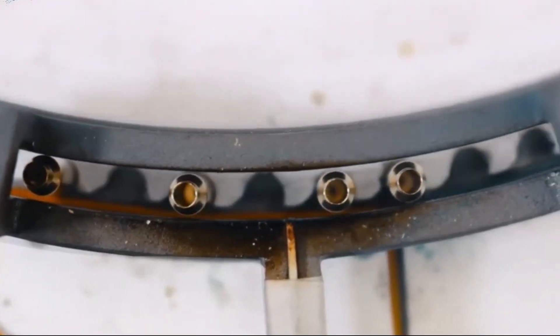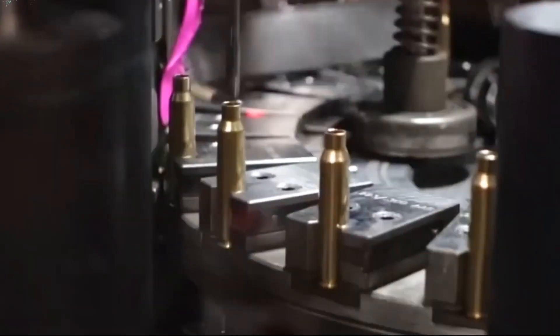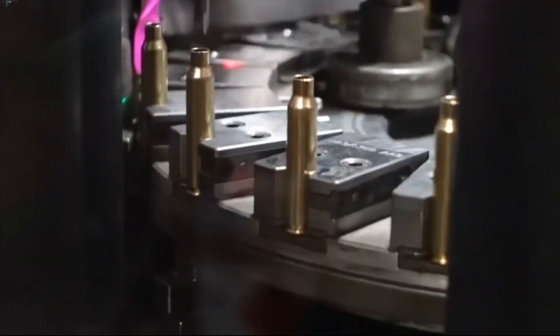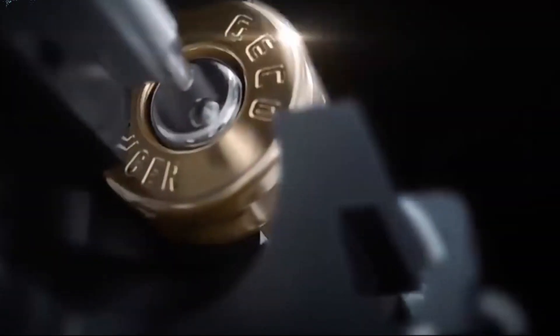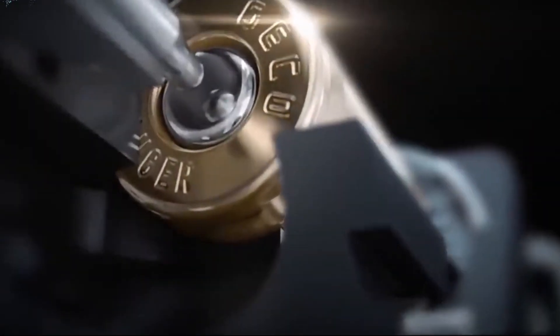The case mouth is then trimmed to precise length and annealed, carefully heated and cooled to achieve the perfect balance of hardness at the base for strength, while maintaining softness at the mouth for proper bullet seating.